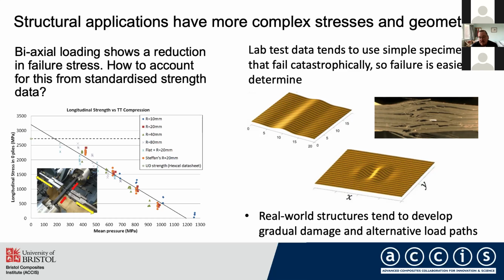However, if we translate that into a real world structure, that wrinkle or waviness is likely to be quite localized. And what we tend to then see is a weakening or damaging of that material, a loss of stiffness, and a load transfer elsewhere. And so our structural failure tends to be in perhaps the less wrinkled material that ultimately starts to carry more load as we get transfer of the load path.